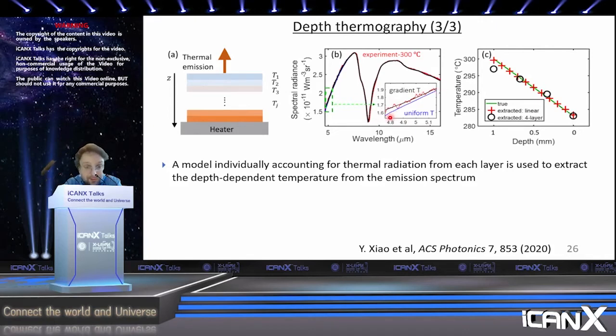The blue curve is a fit assuming a uniform temperature, just finding the best fit temperature. It turns out that the best fit temperature here is about 283 degrees Celsius because, of course, there's this temperature drop from the bottom to the top, and you can see that we can fit the experimental data extremely well. So this is actually already quite impressive experimentally. But if you zoom into this region, remember that at wavelength ranges below about 8 microns, you start to have semi-transparency in the fused silica sample. You can see that the best fit for uniform temperature doesn't exactly match the experimental data.